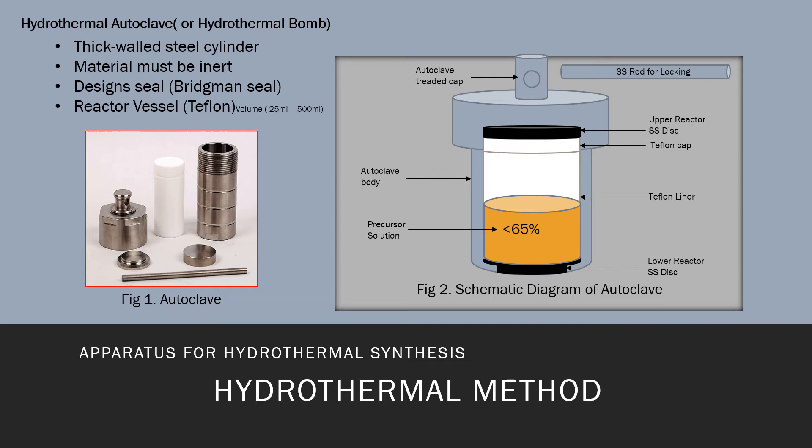It will operate to a maximum of 240 degrees Celsius, and the safe temperature applied is 200 degrees Celsius. Also, the reactor vessels have the capacity range of the volume from 25 ml to 500 ml.